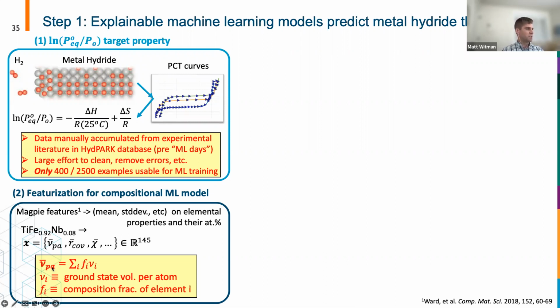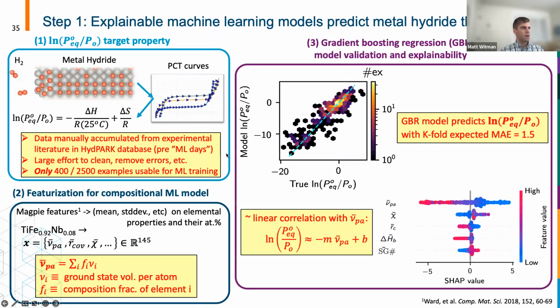Here I'm highlighting one specific feature again. This is the composition weighted mean of the ground state volume per atom. So just one example of a feature that comes out of Magpie. And when we train to predict this log equilibrium plateau pressure, we have a pretty reasonable model that is successful only using these compositional features.